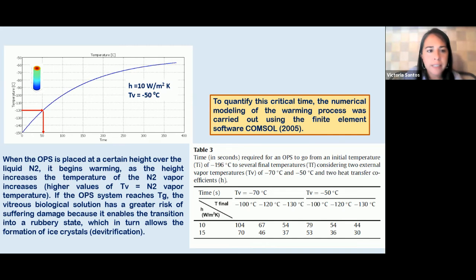How do we quantify this time? How much time do we have? Well, we can quantify this critical time using numerical modeling of the warming process, using, as I said, the software COMSOL with the finite element method. And here you have the figure where we have predicted the temperature versus time in the OPS at a critical point, and it tells us that -120 is reached at about 54 seconds for an H equal to 10 watt per square meter Kelvin, and a nitrogen vapor temperature of -50.